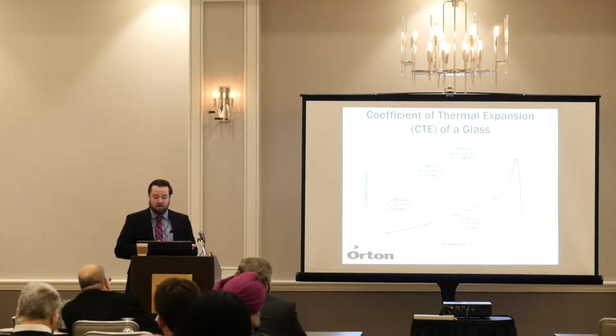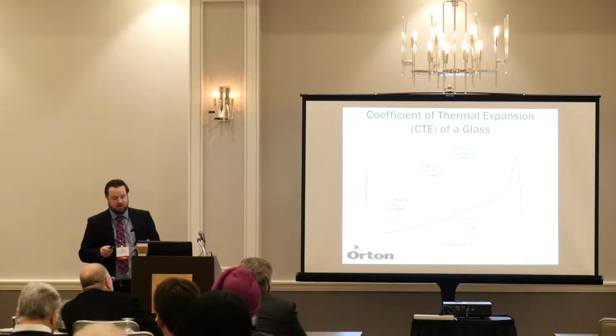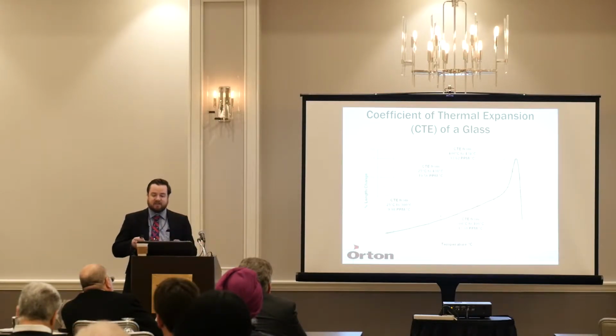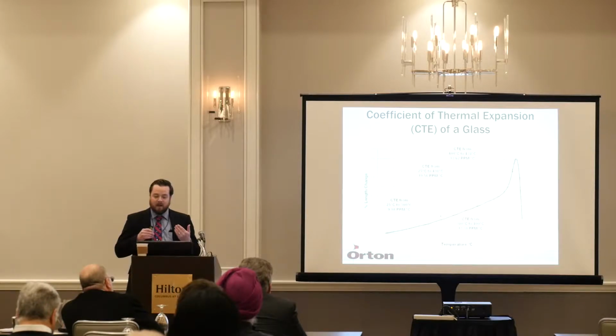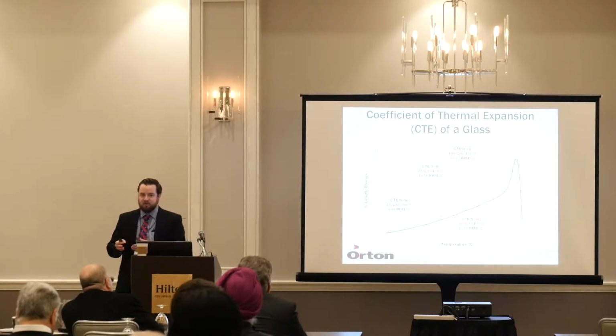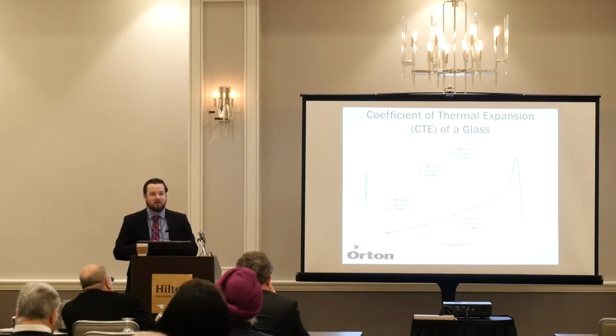25 to 300. If we go a little further, we can jump all of a sudden up to, it looks like, 17.38. So along those ranges, there are different CTEs. It's a tangent material calculation, so it can be skewed one way or the other. It's more to be understood with the actual graph in hand. You don't want to be looking at CTE unless you know it's completely linear. And a lot of glasses do have a lot of linear at the beginning, especially the annealed glasses, but there can be some different changes you see.